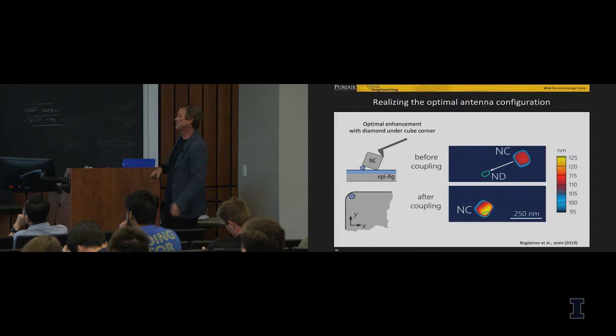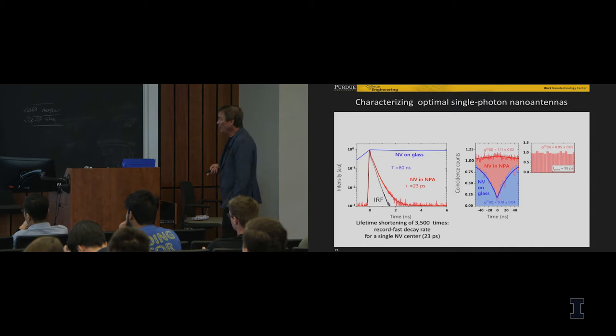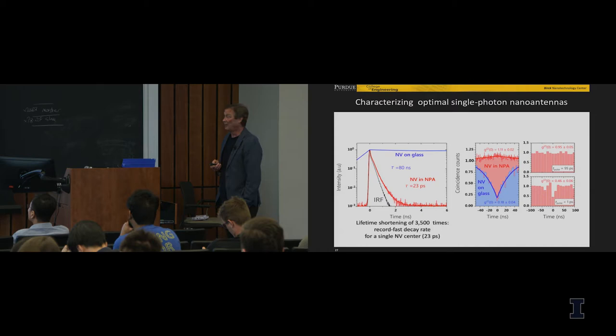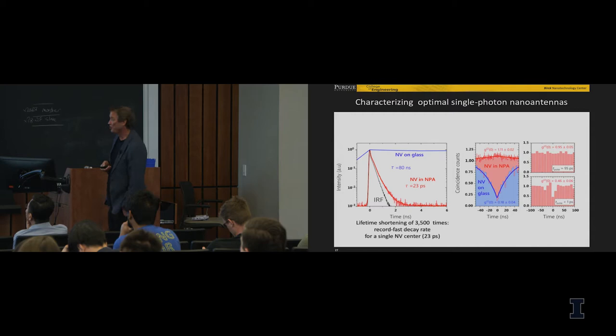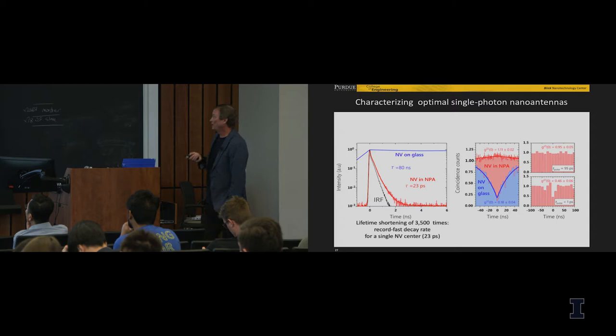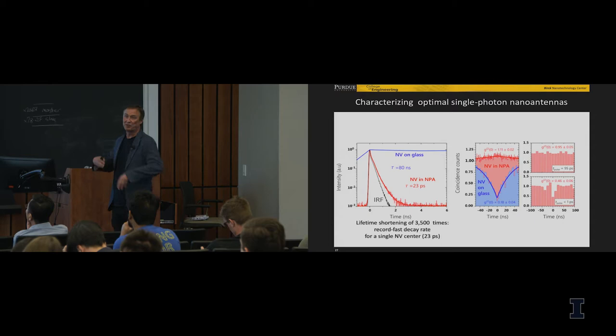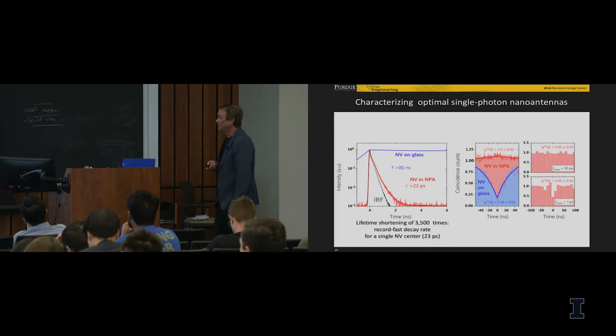And what we obtain is that the time shortens by 3,500. It's a really dramatic one. And the spontaneous emission lifetime is actually 23 picoseconds, which is a record fast decay rate. We cannot even measure the G2 function with CW or picosecond sources because the time resolution does not allow it. We have to use a femtosecond pump to measure this G2 correlation function, which clearly proved that we have an exceptionally high rate of production of single photons.